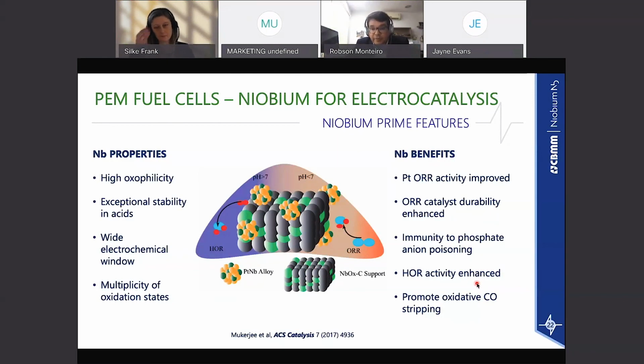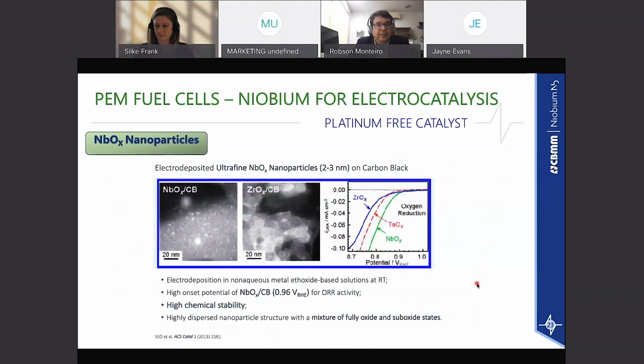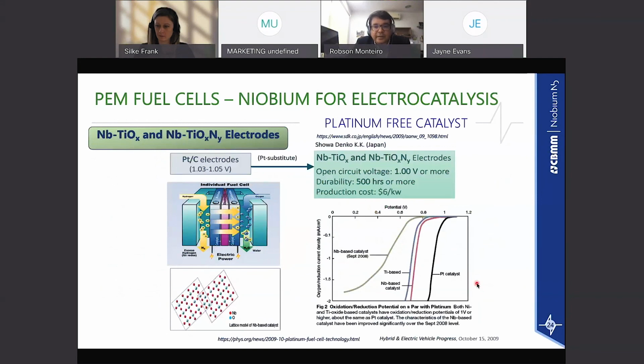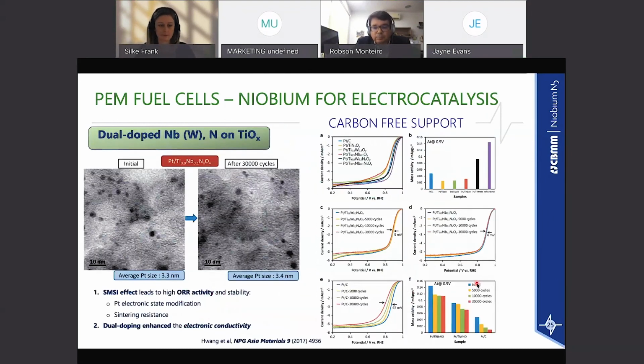So in the end, the benefits that people find with niobium are the ORR activity of the catalyst, and promoting oxidative CO stripping, things like this. People are playing with niobium oxide nanoparticles. This is also for platinum-free catalyst. This is a very good demonstration from a Japanese group of highly dispersed nanoparticles of niobium on top of carbon with very good activity. Unfortunately, the long-term performance is not that good. There was also an attempt a couple of years ago in Japan by Showa Denko to devise commercial titanium oxynitrides. And I will jump a little to the carbon-free supports.